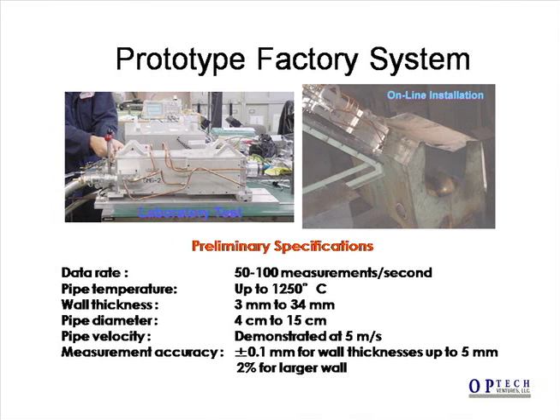The left photo shows the measurement head being assembled in the lab. The head has provision for water cooling and an air purge. The right photo shows the head mounted in position on the line, in this case at 45 degrees. Note that measurements can be made on hot tubes at a temperature above 1000 degrees and moving 5 meters per second.